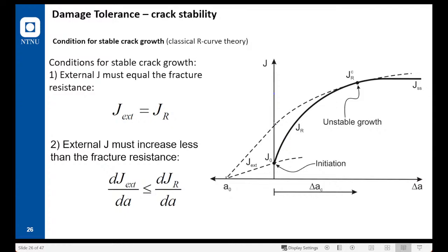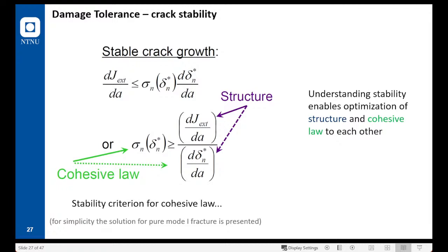Now I will talk a little bit about crack stability. We have said that damage tolerant means that the crack grows slowly. That means that the energy provided to the system, or the energy release rate as the crack grows, should be lower than the derivative of the fracture resistance with respect to the crack length. So this equation should hold. I have skipped many equations in between, and this is our criterion here for crack stability. It's a nice equation because it says that both the material properties, through the cohesive law, and the structural properties will affect the crack stability. Again, both material science and mechanics are necessary to obtain a damage-tolerant composite structure.